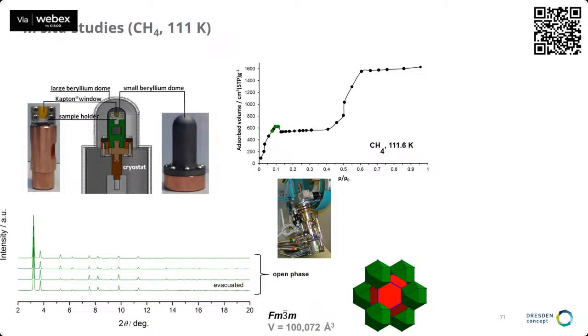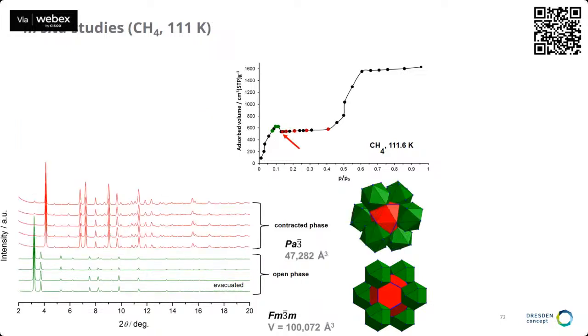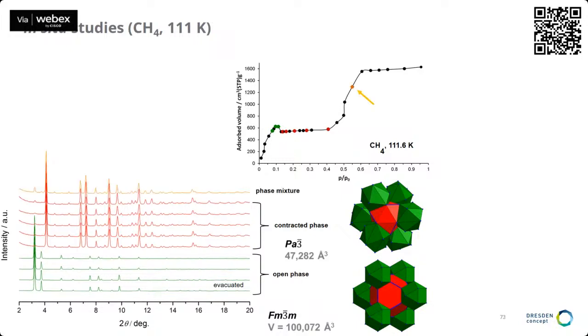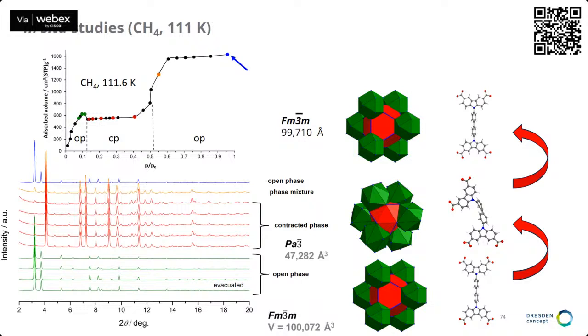But then suddenly when you approach this step, then the structure is contracting. So all the reflections are moving to higher angles, and this huge octahedral pore is contracted from 2.4 nanometer to less than 1 nanometer, essentially. And only when you dose more gas, when you increase the pressure further, then the structure is reopening again. And at the end, you have almost the same powder diffraction pattern as compared to the beginning. And also the unit cell size is almost 100,000 cubic angstrom again as in the beginning. Now, what is happening here to the structure?